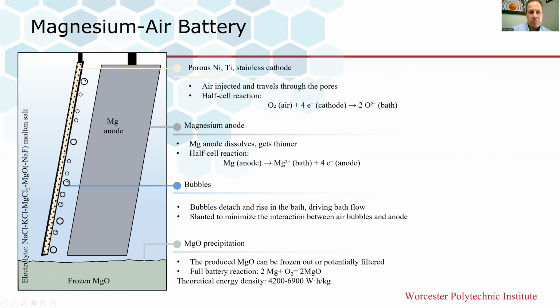The remaining nitrogen and some of the oxygen create bubbles which rise within this gap and provide quite a bit of stirring. And that's important because the solubility of these oxide ions, the magnesium oxide solubility essentially, is very low. It's about 1/2 weight percent. So we have to transport it out and then freeze the magnesium oxide out as we run this cell. So the full reaction is magnesium plus oxygen to magnesium oxide, with an extraordinary theoretical energy density of 4,200 to 6,900 watt-hours per kilogram. And our projected energy density on the pack level, essentially on the container level, is about 1,500 to 2,000 watt-hours per kilogram,